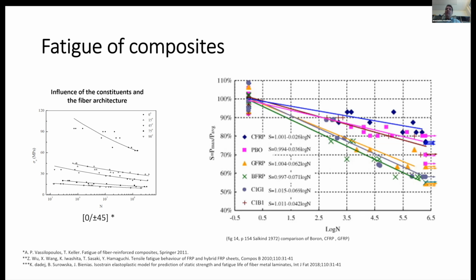We talked also about the influence of the constituents and the fiber architecture. So on the left hand here, I have a graph showing the effect of the fiber architecture. We have materials at 0 degrees, the same material at 15 degrees, and the same material up to 90 degrees. And we see how this affects the behavior of the material. On the right side, I have the same fiber architecture, but different materials, starting with carbon, the blue one, and then glass is the yellow one. And then what else is here? This is biofiber.